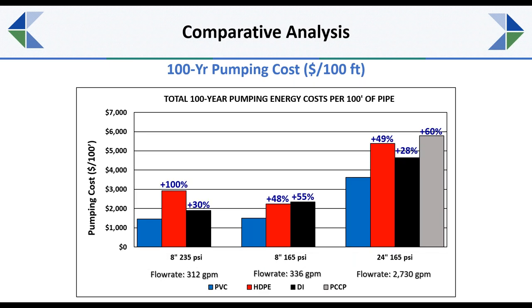Just to give you an idea, we then converted that pumping energy into a pumping cost. So what would the equivalent dollars per 100 feet of pipe, or dollars per 30 meters of pipe, cost? And you can see there that HDPE is a product that requires a very thick wall in order to function, especially at higher pressures. That can significantly affect its hydraulic characteristics, reducing the inside size of the pipe. And then ductile iron pipe, as the mortar lining degrades over time, does increase the pumping cost over time.